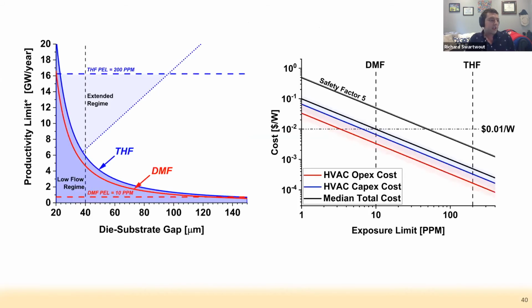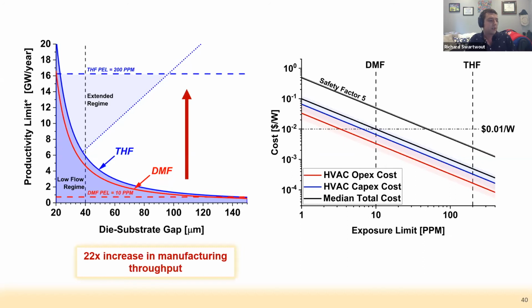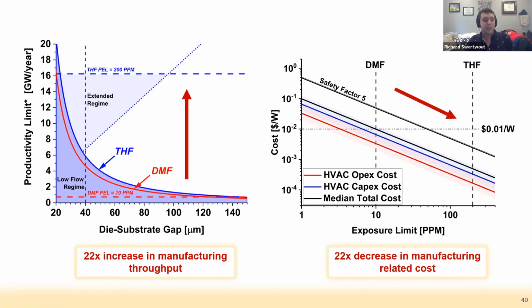So again, for a 1,000 cubic meter sized manufacturing center, you get a 22 times increase in manufacturing throughput. This is not based on theoretical limitations from the solution. Both THF and DMF have very similar low flow limits, but obviously very different PEL limits, as marked with the blue line. From a cost perspective, you also get about a 22 times decrease in manufacturing related costs.